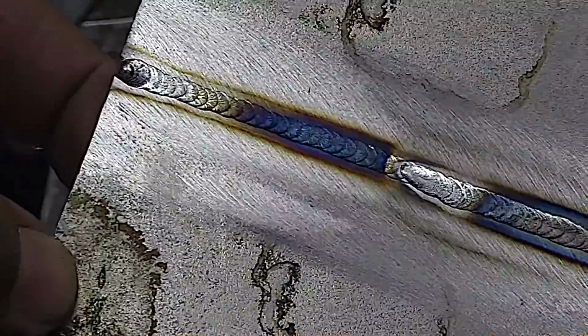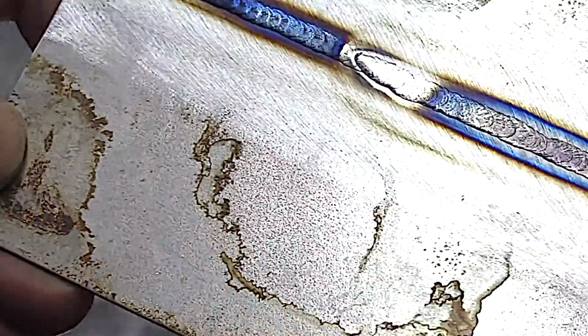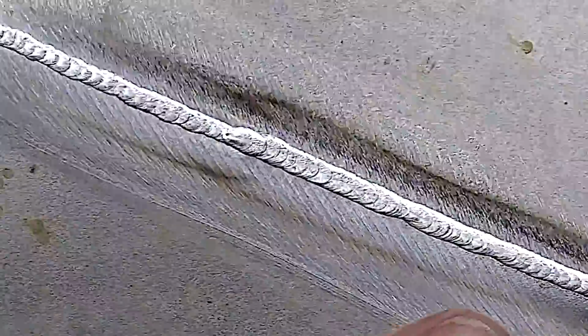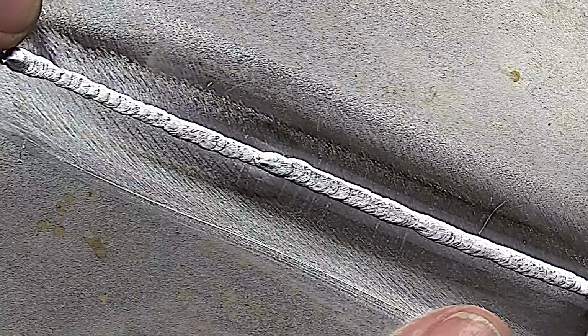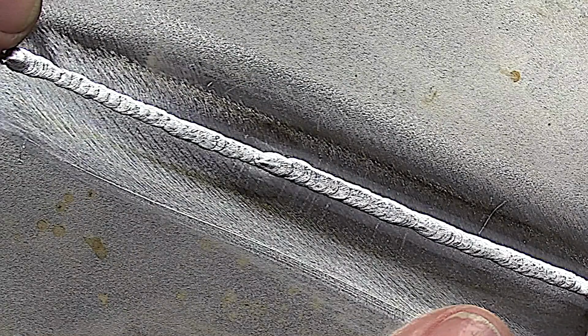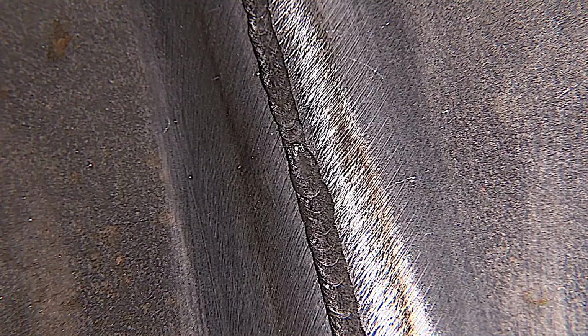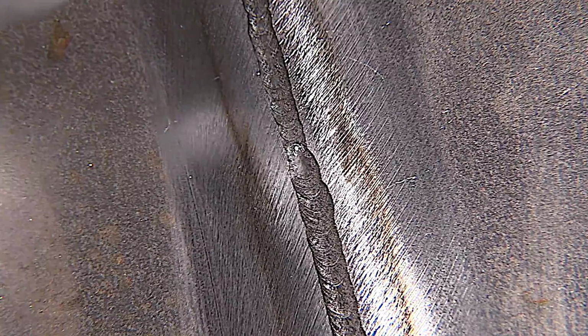Now the reason I required that taper off thing in the middle of the test joint is because that's the most likely place for a crack, especially on crack-sensitive alloys. Let's take a close-up look at that. And now let's take an even closer look with some magnification, and let's zoom in a little bit. That's where you're likely to have a crack right there.